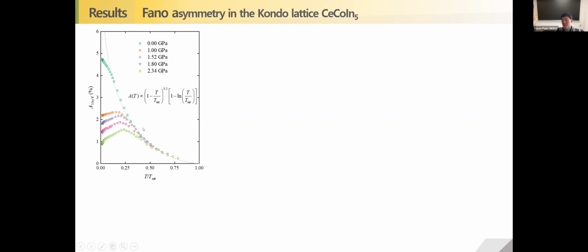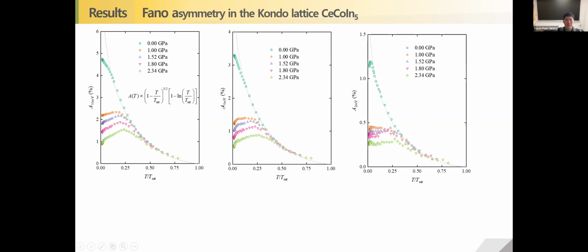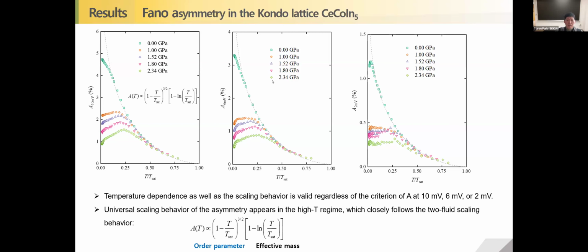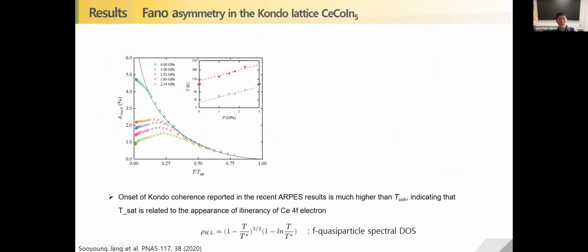In order to see whether this asymmetry scaling behavior is due to our random criterion, we used a 6 millivolt criterion and a 2 millivolt criterion. As you can see, these all show pretty much similar scaling behavior at higher temperatures. The dashed line is the fit using a two-fluid scaling model. The asymmetry consists of two terms, namely the effective mass times the so-called order parameter, or the fraction of the conduction fluid, which explains the data pretty well.